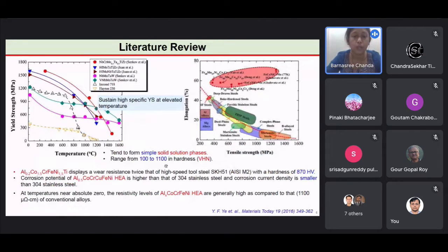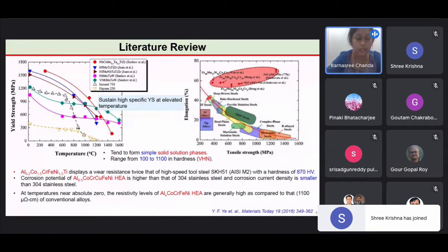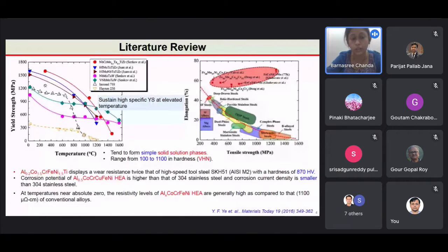There are many important mechanical and functional properties possessed by high entropy alloys. Some of them are yield strength versus temperature, as shown in the plot, where a comparison of high entropy alloy with conventional superalloy has been made, where we see that high entropy alloy has sustained very high specific yield strength at elevated temperature. Further, the elongation versus tensile strength plot, comparing the high entropy alloys in this red zone with various types of steel, shows that the high entropy alloys have excellent values of yield strength with elongation.